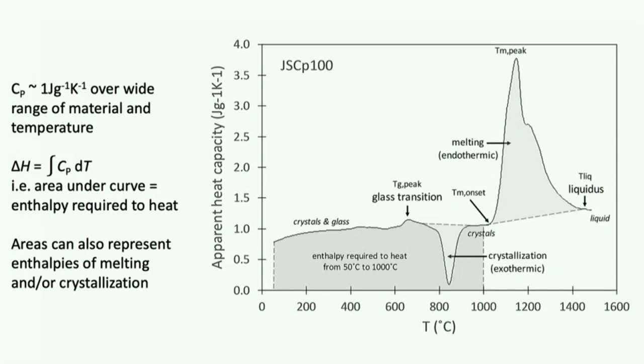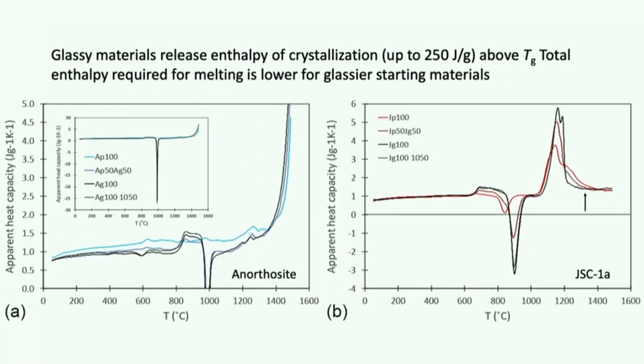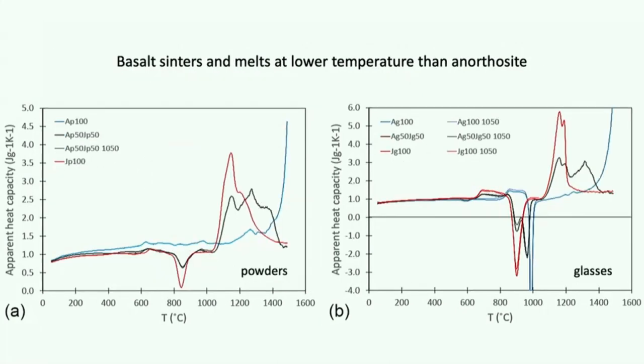That is endothermic. And so this area in here is the energy released during crystallization. This area here is the energy required to melt. They're very different because here we only had some glass in the sample that crystallized, and here we had to melt all of the crystals, both the ones that were there to begin with and the ones that grew. All right, so the cliff notes here is that glassy materials release energy when you heat them up, which, if you're trying to get to a high temperature, saves you energy. The enthalpy of melting is lower if you start with glassy material.